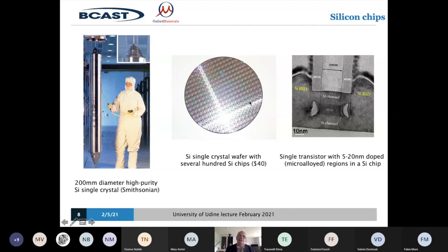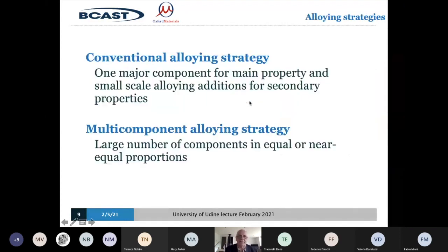So that's the history. Now, all of that development, which has been fantastic and wonderful, and massive technological development, has been based around what I call conventional alloying strategy. That means that we nearly always, for our materials, take one main component for the main property and add small amounts of additional alloying elements or components for secondary properties. It's very sensible, and that's why we've done it that way. So, for instance, the nickel alloys for the jet engines, nickel is there for the high temperature resistance, but we had to learn how to add small amounts of aluminium or titanium to give it the strength, and a little bit of chromium to give its corrosion resistance. Secondary properties to the high temperature properties.